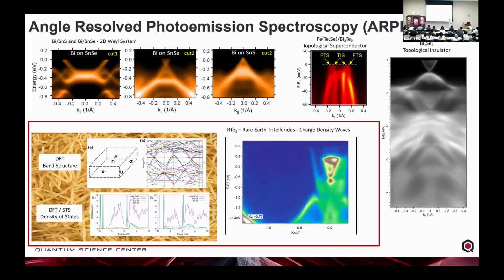But now in STM, you can actually do dI/dV and look at the density of states. And so the difference between what we're seeing here is that the density of states is nothing more than integrating this along momentum. And so if you integrate this along momentum, you will get the density of states, which you can then compare with your STM or STS measurements.